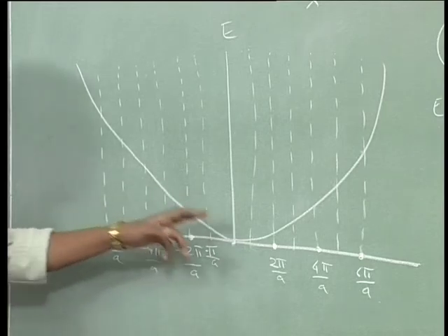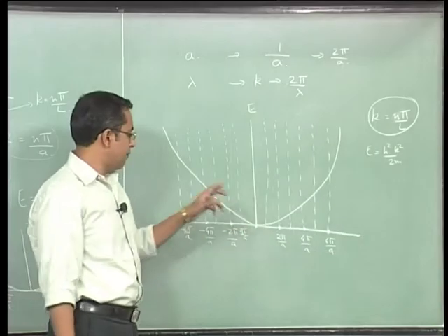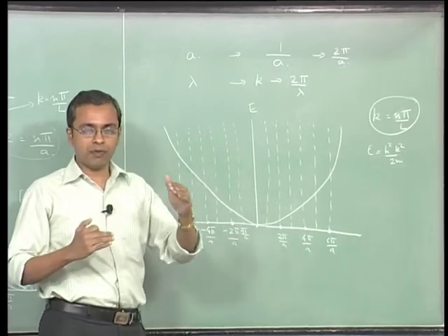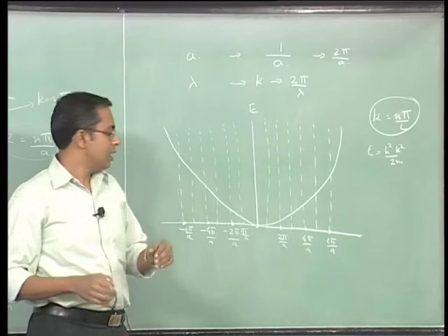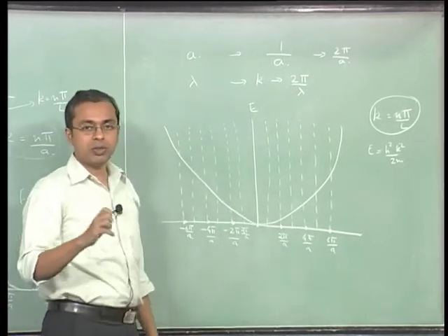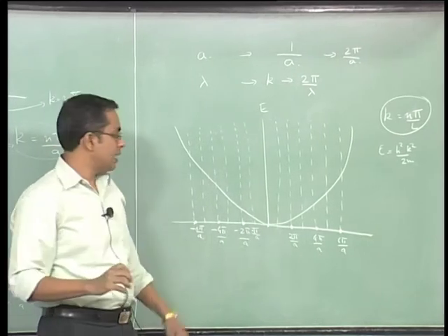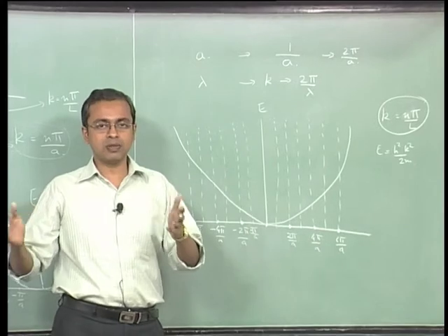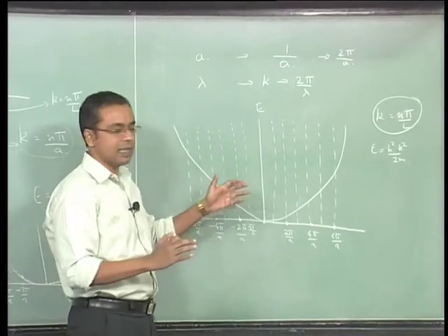So at all of these locations diffraction is occurring, and wherever diffraction occurs it turns out that certain energy values become forbidden, alright. Therefore at Brillouin zone boundaries this E versus k relationship begins to distort, okay, and it is this distortion that results in the band structure of the material. Right now I am saying that in a general sense.